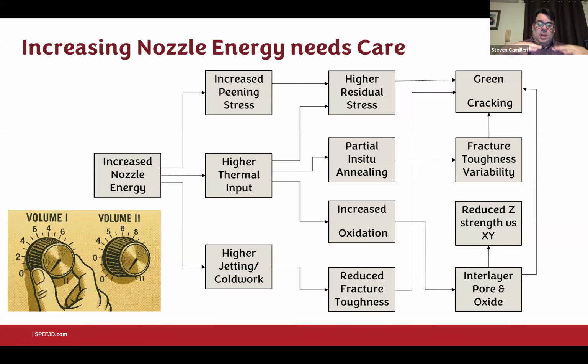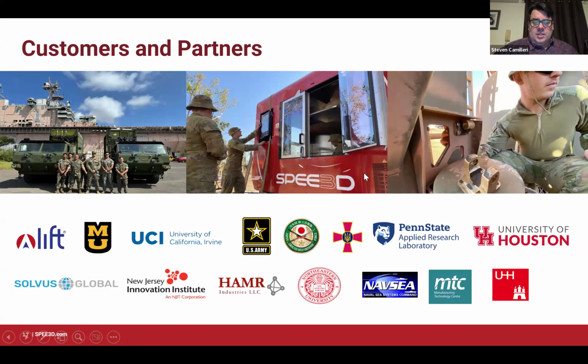And what that will mean is you'll have great strength if you've been spraying this way. You'll have great strength laterally, but as you come in between the layers, you'll start to see reductions in strength. So in cold spray AM, as opposed to just cold spray, we have to think much more seriously about those planes of oxide and managing those, because we get poorer properties typically in Z. So that's to the extent where when we're developing a new material, we won't even look at XY properties until very late in the piece. We will just look at Z. It's a dominating factor. All right, that's the end of my presentation.